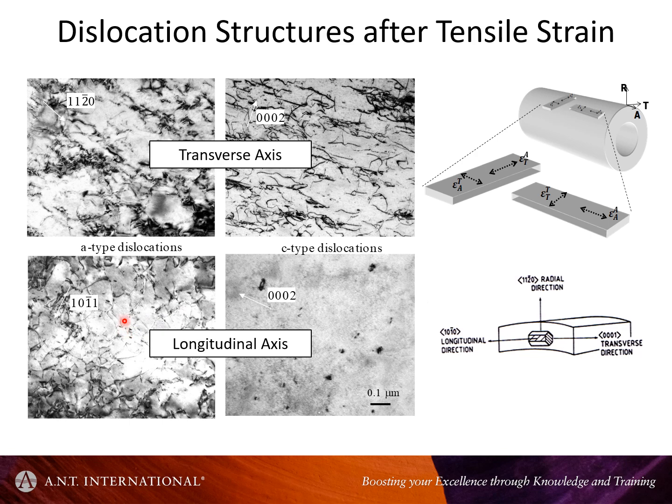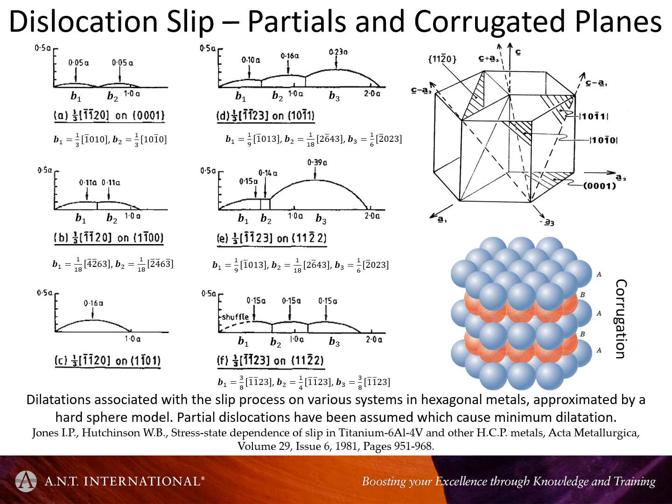And the two types of dislocations are most easily illustrated by using a basal pole diffraction vector. In the one case, we have a C component, and they show up as dark lines. And in the A-type dislocations, we have no C component, and they don't show up at all when you image with a basal reflection. So what am I talking about? I guess I could have introduced this earlier, but it's difficult to put everything in all at once.